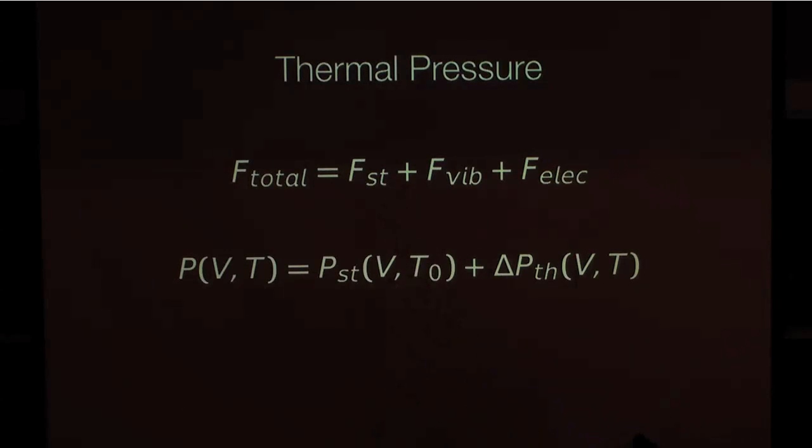Reference temperature. Now, for the thermal effect, there are many different ones. For silicates and ionic solids like Earth mantle materials, not the core, the thermal effect mostly comes from the vibration of atoms at different temperatures.